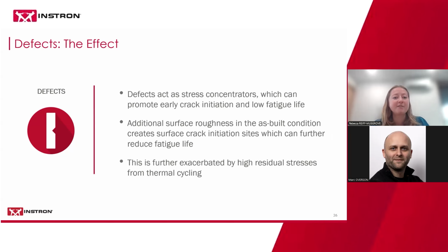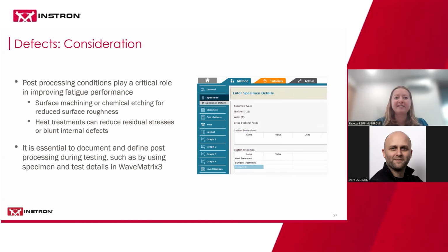Beyond this, we're not helped, and the lower fatigue life is further exacerbated by high residual stresses from the thermal cycling and the high thermal stresses during the additive manufacturing process that, when they want to be relieved, also cause early fatigue and early cracking. So that doesn't all sound great. So what do we have to actually consider when we're looking at defects?